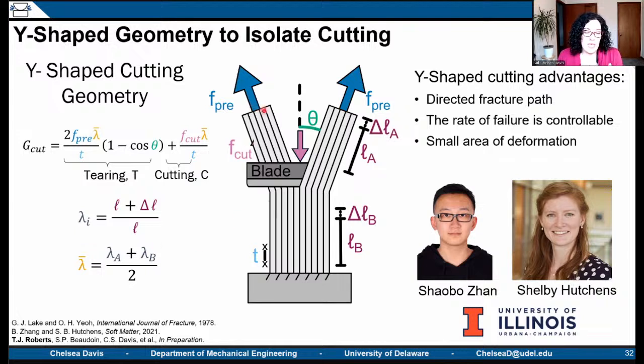So in Y-shaped cutting, we take a sample, we form it into a Y geometry, and then we apply a small preload to the two legs of the cut. And then we're going to shove a razor blade, or a blade of some sort, into the material. We're going to measure the displacement of our material and the force required to displace the blade into the material. And that's the experiment. From that, we should be able to get a cutting energy, which is going to allow us to then deconvolute the tearing energy, or tearing component, if we can get this half angle small enough, from the cutting component.